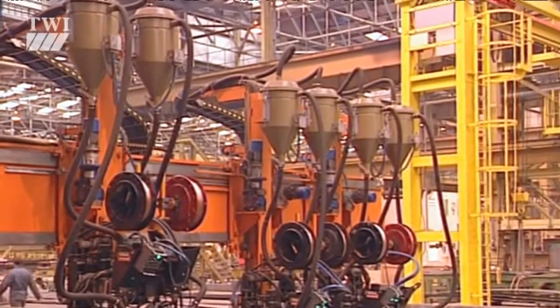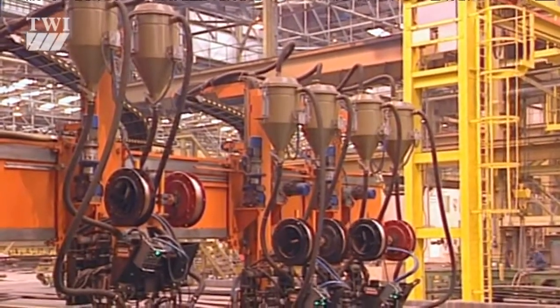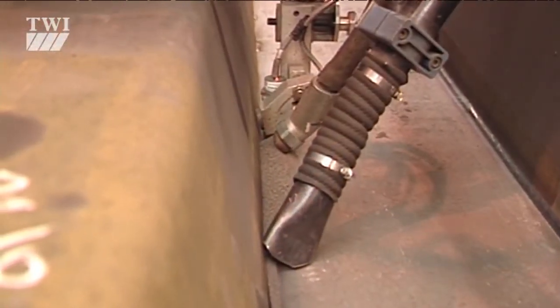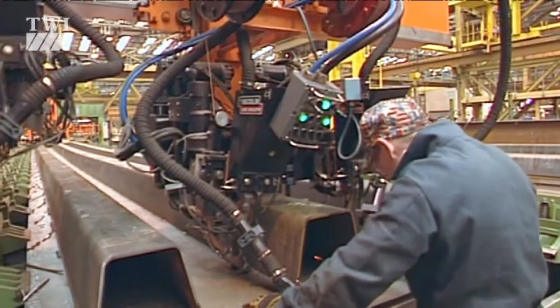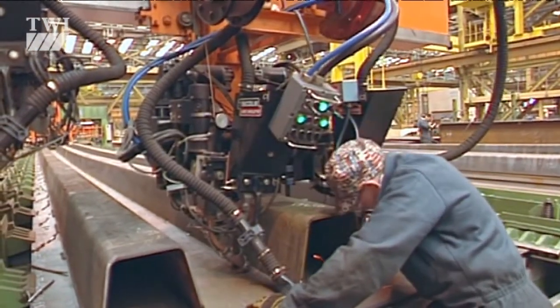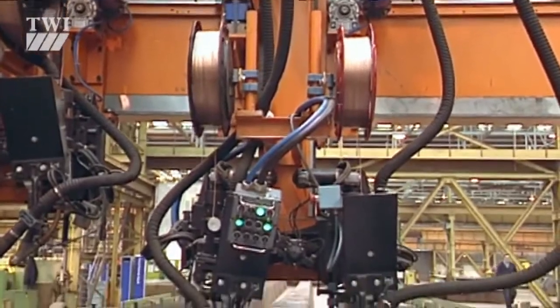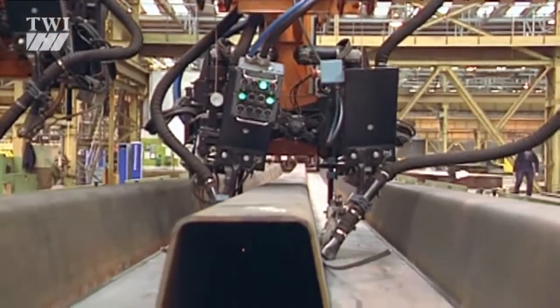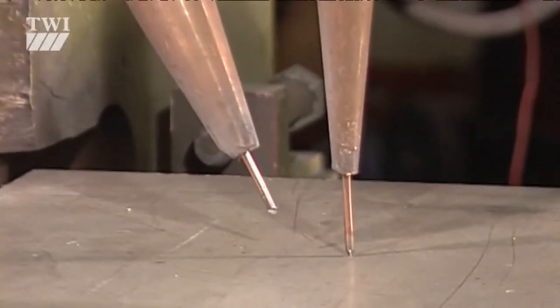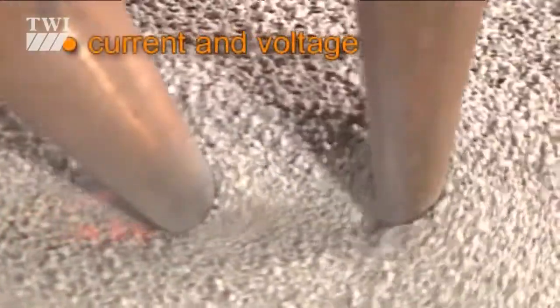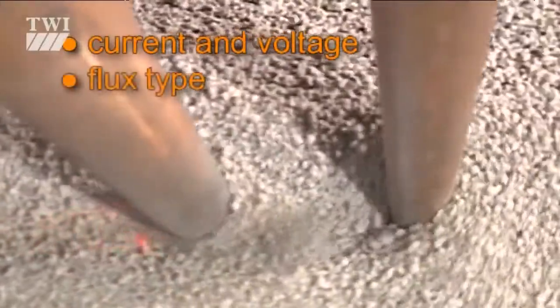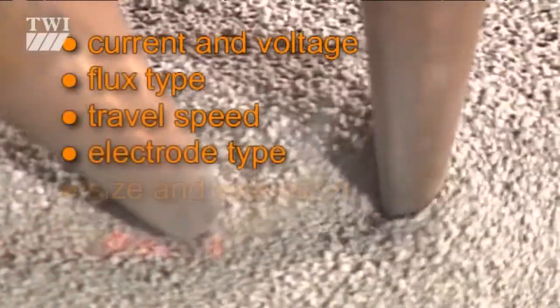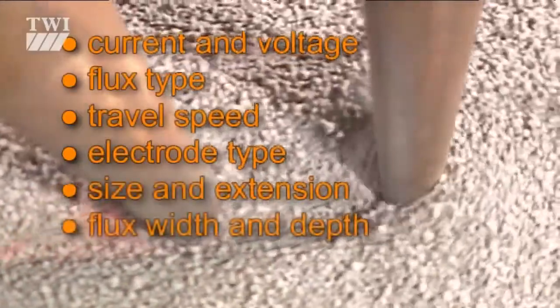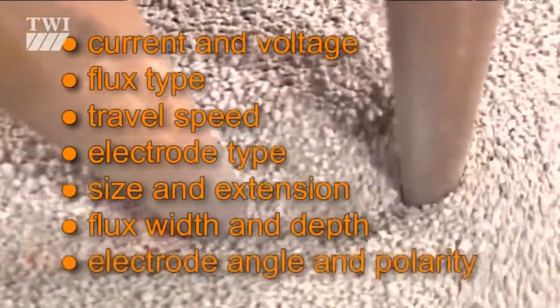SAW is known for its use with high welding currents, which produce deep penetration, high dilution, and high deposition rates. Generally, a DC positive polarity is used up to 1000 amps. At higher currents, or in the case of multiple electrode systems, AC is preferred to avoid arc blow. It's also common to use a combination of both, with a DC leading arc. The process variables include welding current and voltage, flux type, travel speed, electrode type, size and extension, flux width and depth, electrode angle, and polarity.